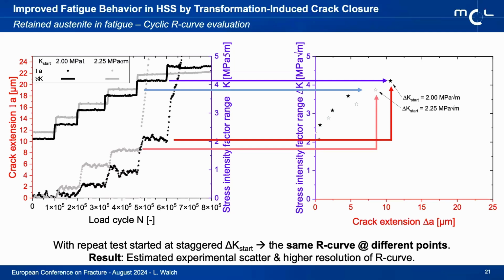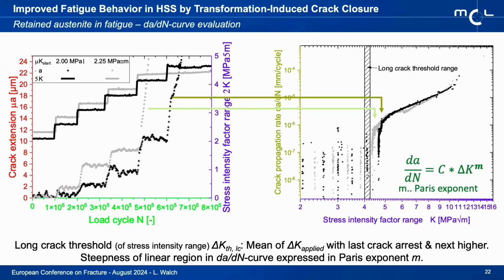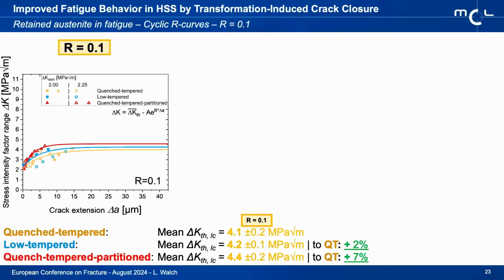So if you look, for example, at the cyclic R curve, which is usually the function of stress intensity factor range at which crack arrest occurs, dependent on the fatigue crack extension, we can see that if we move along the same cyclic R curve in a material state at different stress intensity factor ranges, we have twice the resolution with just 2 tests. And also, of course, we can get an overview of the experimental scatter, which is quite important in fatigue testing itself. The same is true for fatigue crack growth diagrams. We get a good overview over the long crack threshold, also Paris regime, because that shouldn't change with our testing approach. And this brings me, because we're short on time, to the results.